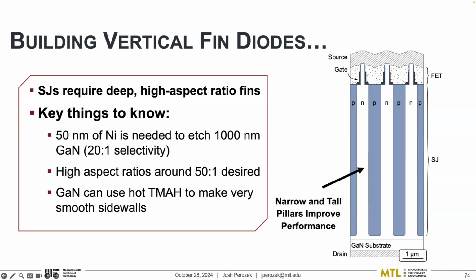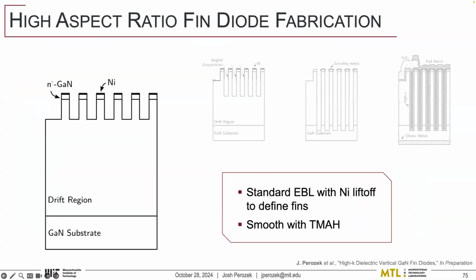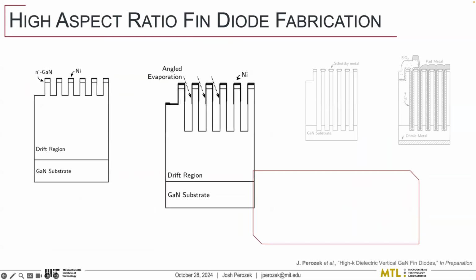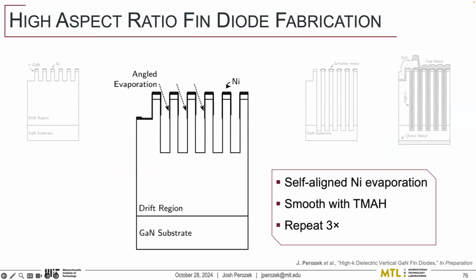So we took these ideas and we decided to combine them with the fabrication techniques that I talked about in the first section of this. So we start by just making our normal fins like we would for any transistors. We use 50 nanometers of nickel, we etch a micron fin. We want to go way deeper than that. So we're able to use those same mushroom structures that we created and remask the gallium nitride.